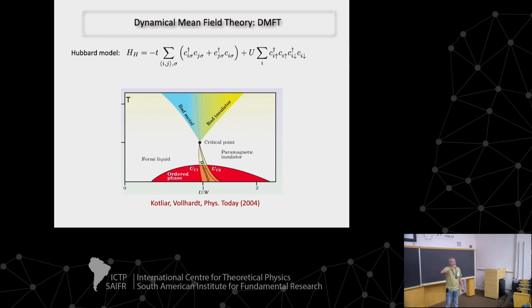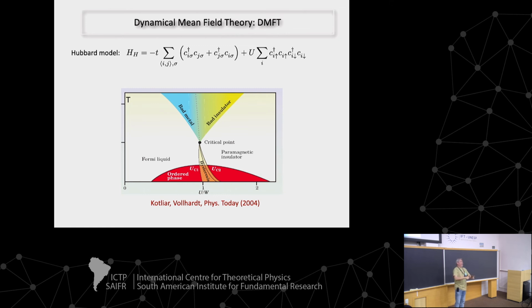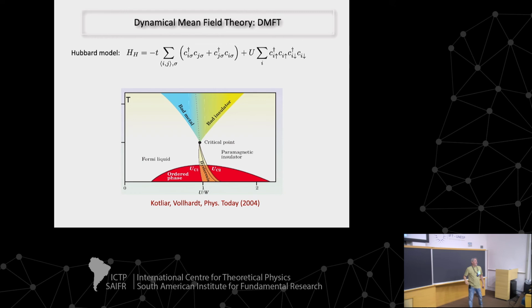Because in dynamical mean field theory, you neglect spin correlations, basically. So if spin correlations between sites are very small, as in a frustrated model, for instance a frustrated lattice, then you get this inclination, this slope here. If you do the extension where you take into account spin correlations, because you solve the cluster exactly, then this thing goes this way. It's basically an entropy-energy consideration that tells you that as you go up in temperature, you go from metal to the insulator, or the other way around. Okay, but other than this, it's a well-defined problem with a well-defined answer and so on.